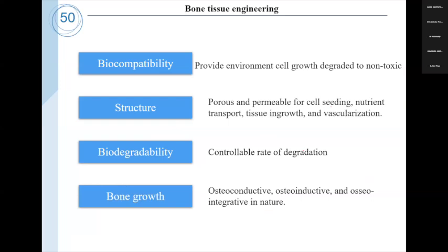The pore-rich structure allows the cells and nutrients to move well to the inside and grow. It should also be possible to control the biodegradability, the degradation of the scaffold. If the scaffold breaks down too quickly, it disappears before the cell grows, so it cannot provide support. And if it breaks down too late, it may need reoperation to remove the scaffold after the cell grows up, or the cell may not grow completely.